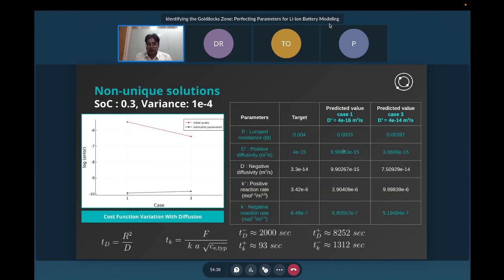Coming to the non-uniqueness part, while we were doing this exercise, what we also realized was that when we optimize these parameters, the sets of parameters that we obtained, depending on the different initial guesses, were not all close to the target. And that essentially tells us that even though we could capture the voltage profiles on the pulses, there are different sets of parameters that can lead to the same kind of voltage profile. Now, how do we believe that the parameters that we have estimated are the parameters that represent this current cell accurately?